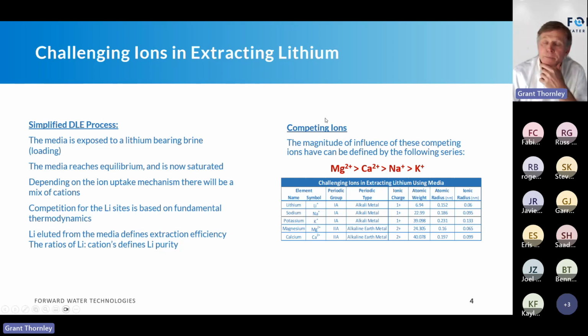What we're seeing here is competing ions. An ion exchange has a functional site. Think of it as a magnet that's going to attract the lithium. But other ions, which are similar to lithium, are also going to compete and try to get onto that site. When we look at the affinity, or the attractiveness, to get onto that site, magnesium has the highest affinity, followed by calcium, sodium, and potassium. This is why, when you look at DLE efficiencies or testing, you typically don't see a complete analysis of all the ions.